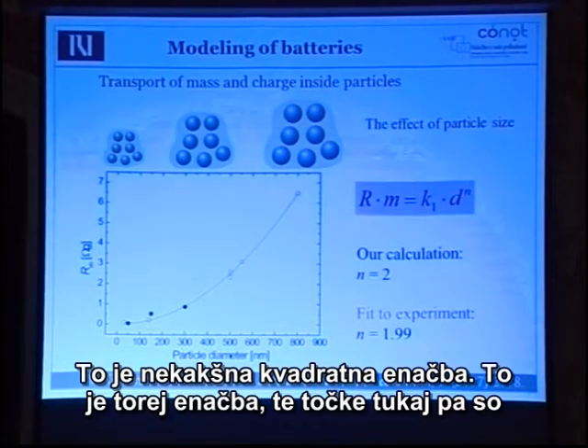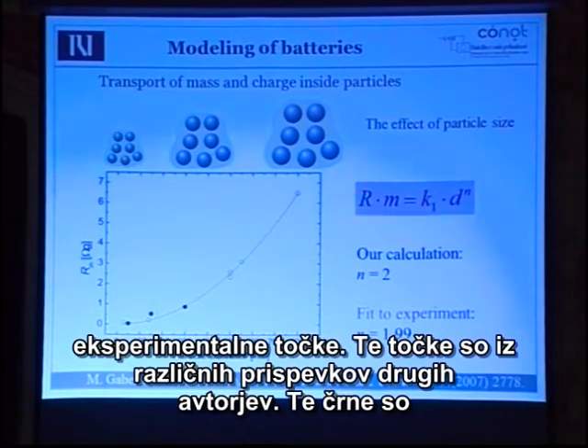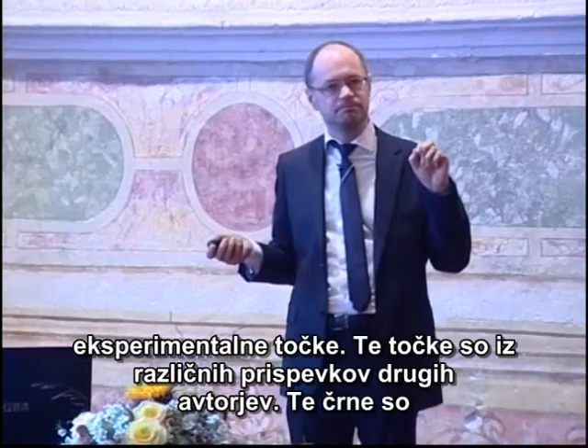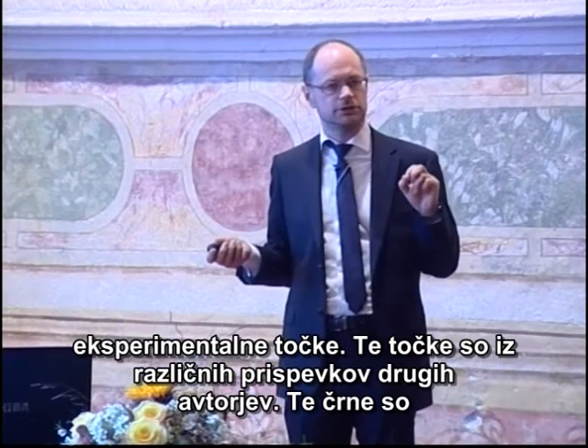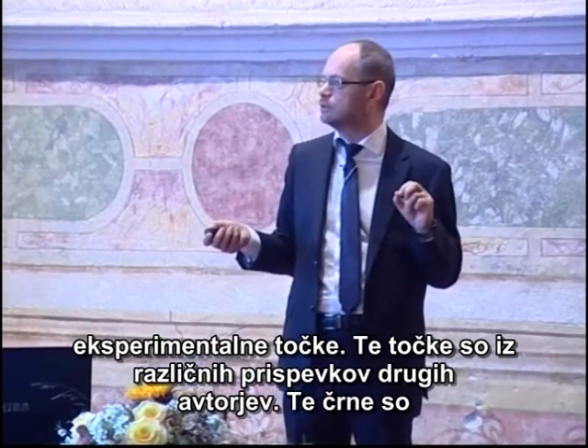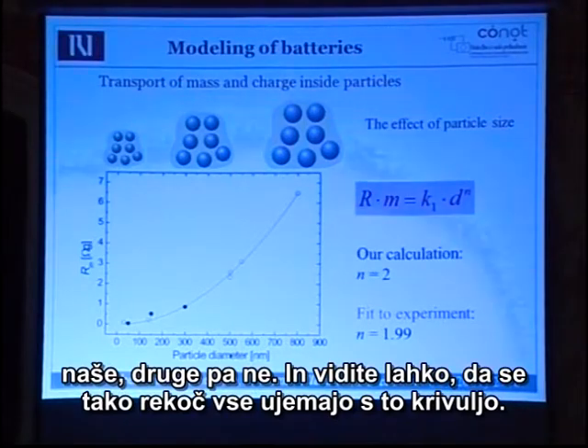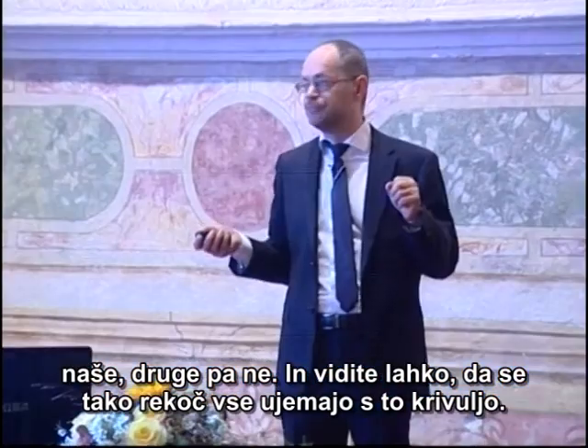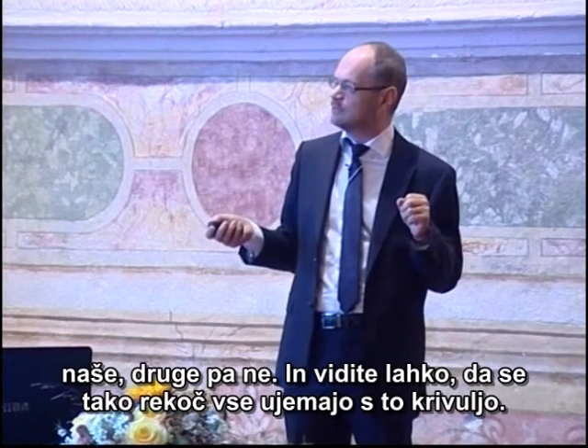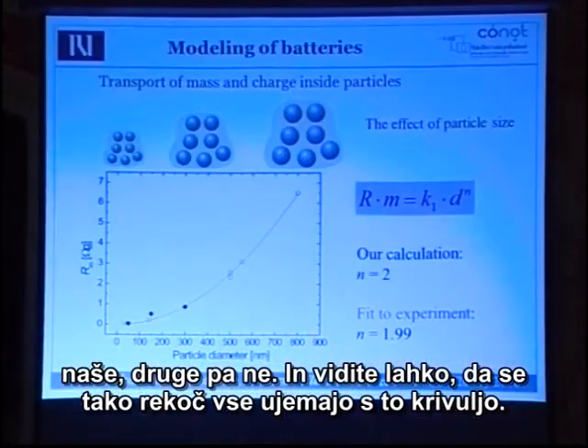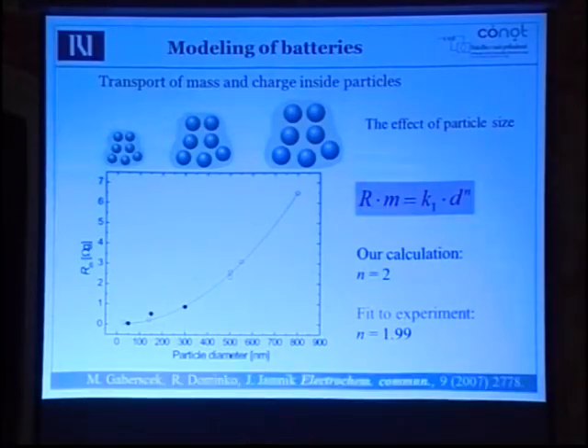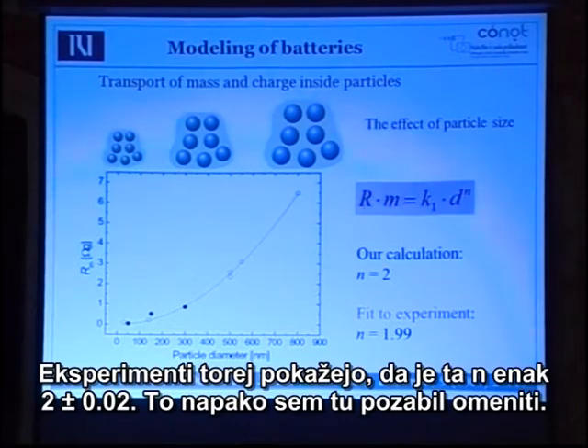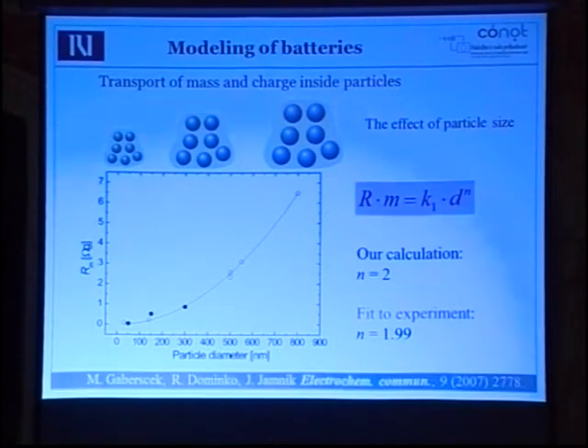So this is the equation, and the points here are experimental points. These experimental points are from various papers of other authors. The black ones were made by ourselves, but the others were made by other people. And you see that all of them fall on this curve, and the fit shows that this N was 1.99 plus or minus 0.02. I forgot to add this error here.